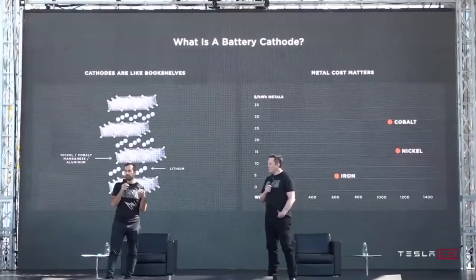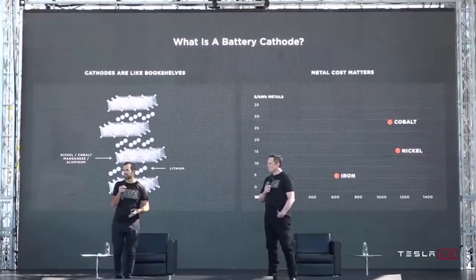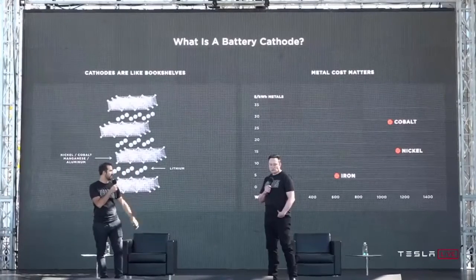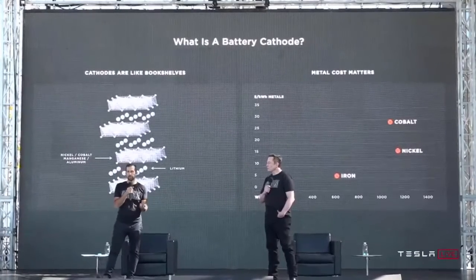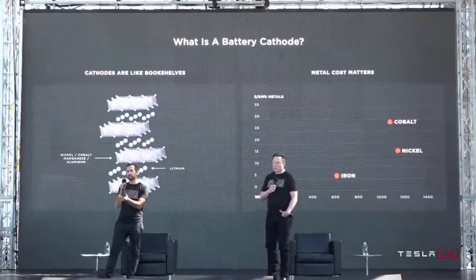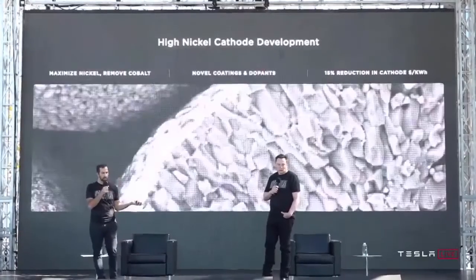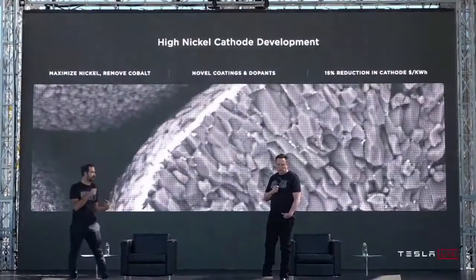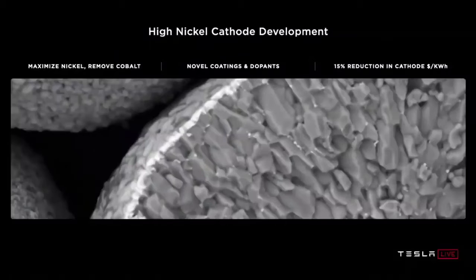But one of the reasons why cobalt is even used at all is because it is a very stable bookshelf. And the challenge with going to pure nickel is stabilizing that bookshelf with only nickel. And that's what we've been working on with our high nickel cathode development, which has 0 cobalt in it. Leveraging novel coatings and dopants, we can get a 15% reduction in cathode dollar per kilowatt hour.